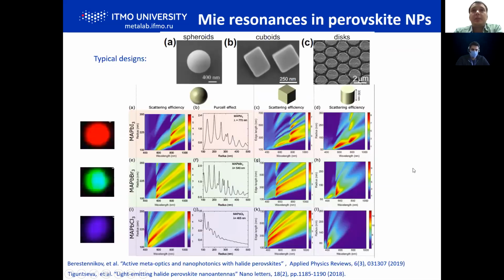And regarding the basic optical properties of perovskite nanoparticles, we should start from very basic things like analysis of scattering properties of perovskites of different compositions, from low band gap to wide band gap perovskites, and for different shapes: sphere, cube, or cylinders. And you see here the calculations from Mie theory, scattering efficiencies, and even the Purcell effect in nanoparticles is calculated, and one can see various resonances, Mie resonances, in all these shapes. So it means that we can fabricate particles and expect some resonant response from them.